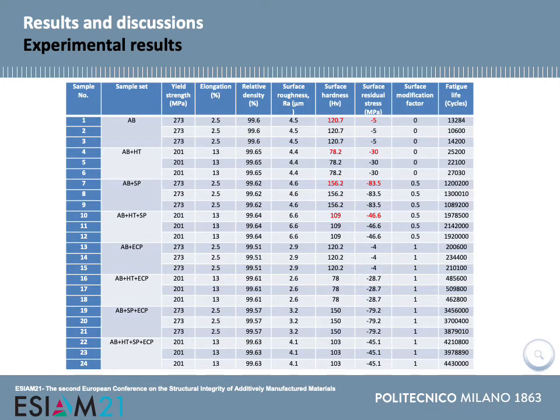Here you can see the obtained results of different experimental characterization listed in the table. You can see the increase of surface hardness and residual stresses in the shot peened samples, and also it was observed that ECP did not have any considerable effect on the hardness, residual stresses, and also density.